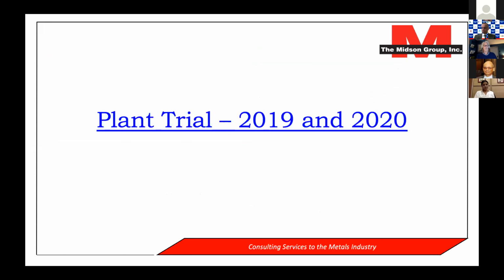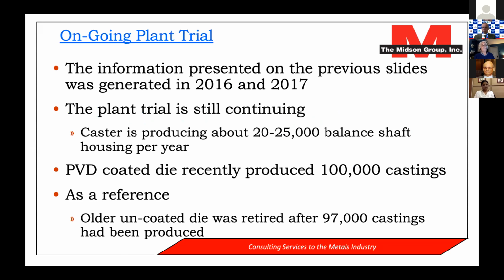So as I said, that was done back in 2016, 2017. The plant trial is continuing. And so now here's some more recent data from 2019 and 2020. As I said, the information before came from 2016, 2017, but because the caster is only producing somewhere between 20 to 25,000 balance shaft housings per year, they're still running the die. So the plant trial is essentially still continuing. And the PVD coated die recently produced more than 100,000 castings in the same die.